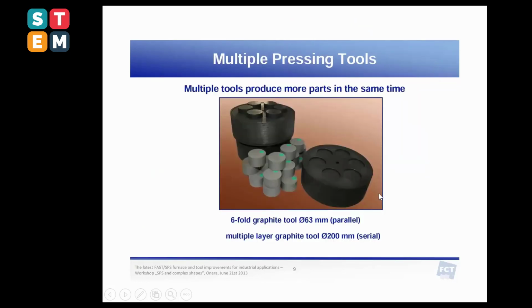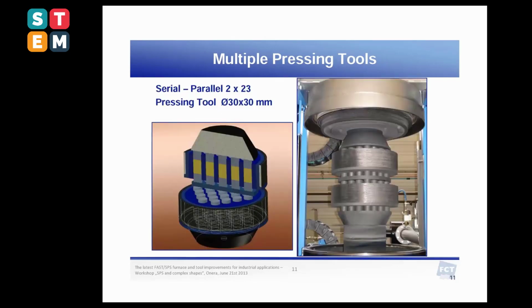And when they do that, they make some tests. By designing these multiple process pressing tools, they were able to produce many samples like you can clearly observe here in this slide. And then they show that if they combine, after designing the new mold, series in parallel, they were able to prepare 46 pellets at the same time, like you can clearly observe here. The sample is located between these two tools.